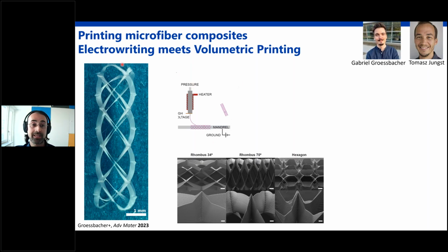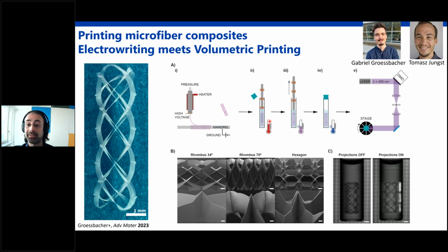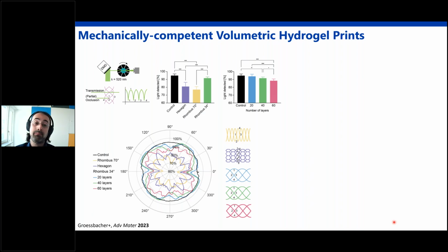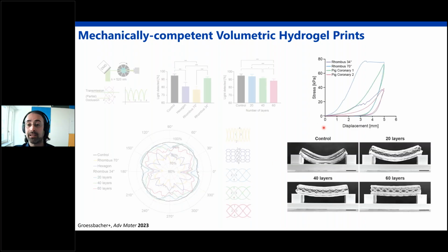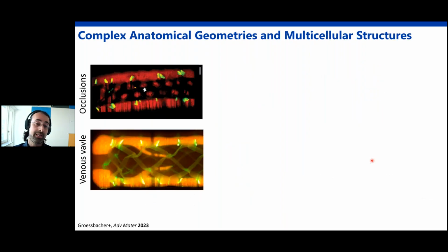And what we did here was print these mechanically stiff, reinforcing meshes out of PCL, place them into the vial of the volumetric printer, and subject them to different projections to pattern arbitrary structures interwoven with these reinforcing elements. Of course, we first have to characterize how the light is being impeded by the opaque mesh. Once we know this path, we can correct it with the software, and then eventually obtain these vessel-like structures, which, when combined with the meshes, show improved mechanical properties comparable to those of a pig coronary artery. The advantage of combining these two techniques is that now we can make paths that are very complex to make by simple casting.